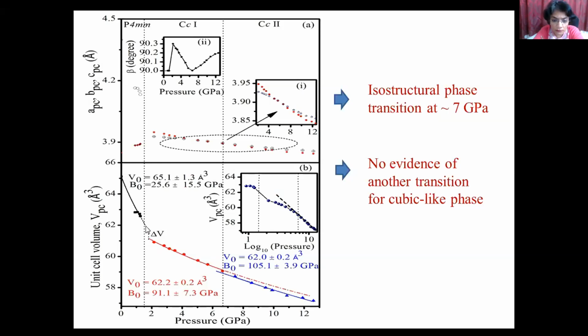Here we can see that from P4M to CC phase, there is a clear first order phase transition, and at the point at which the 2-2-2 peak profile gets reversed, there is a peak signature, which is not here in linear pressure, but when we plot log of pressure, we can see that there is a departure from linearity. Talking about lattice parameters, we can see that the C and A parameters get reversed above this 7 gigapascal.